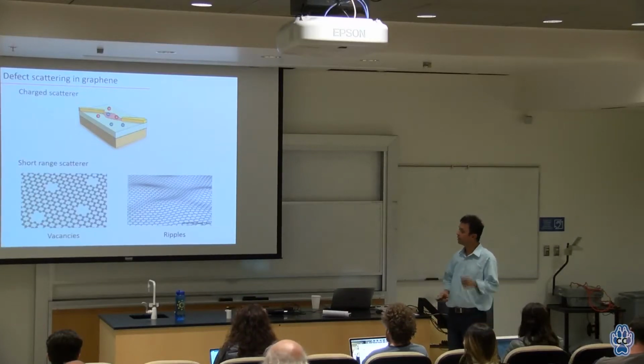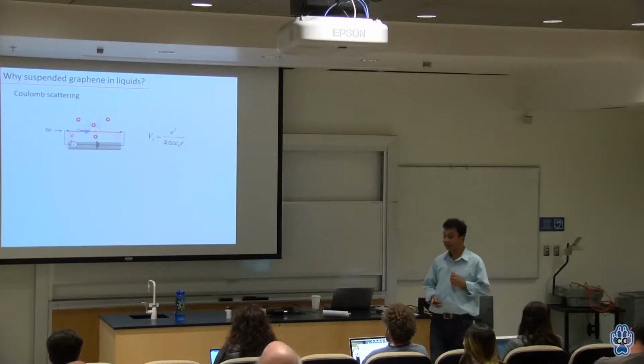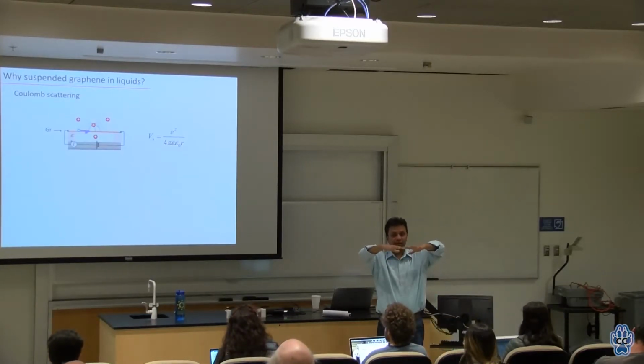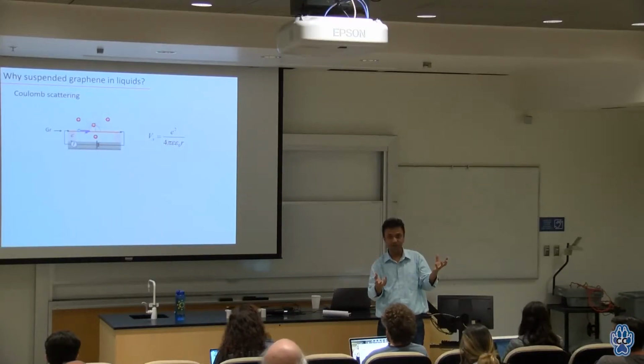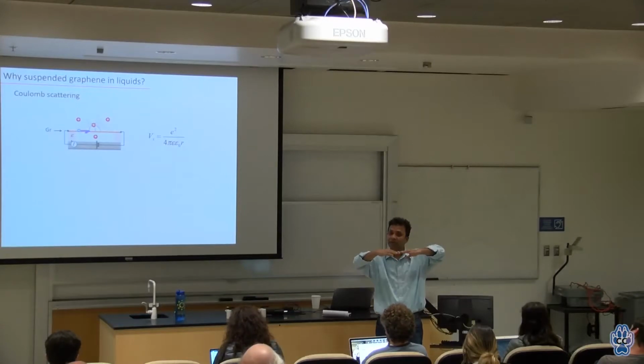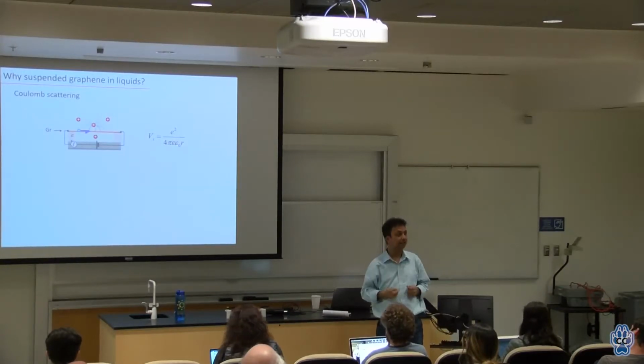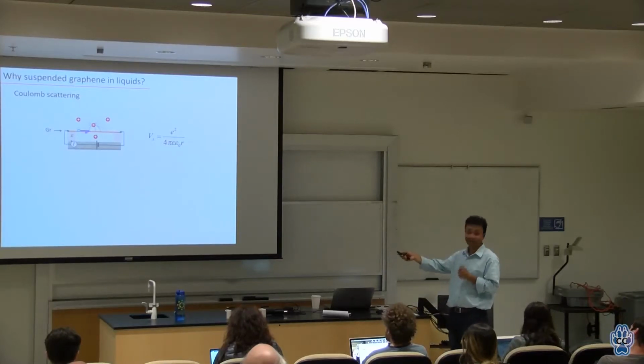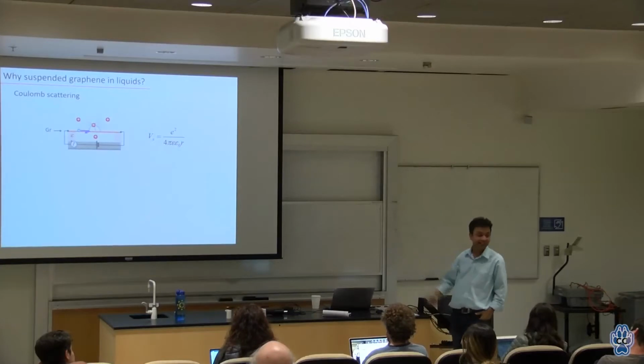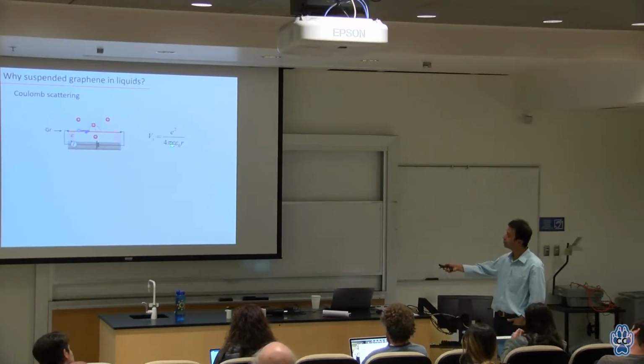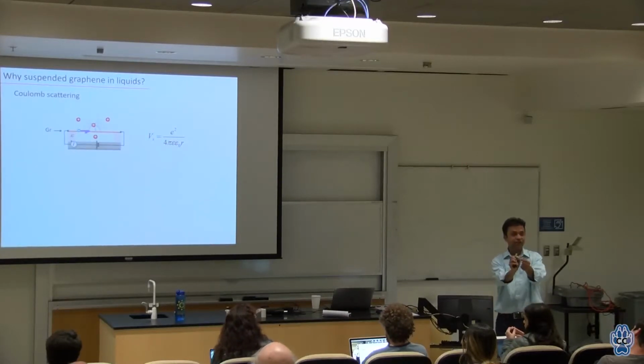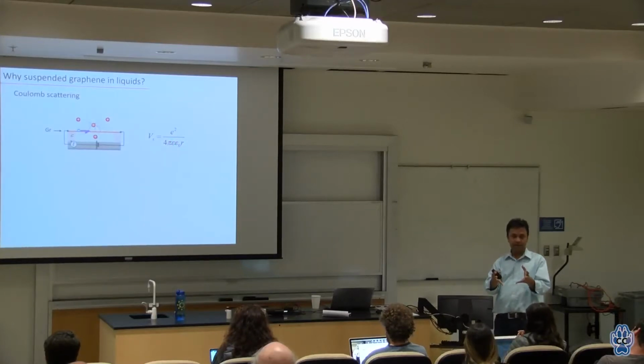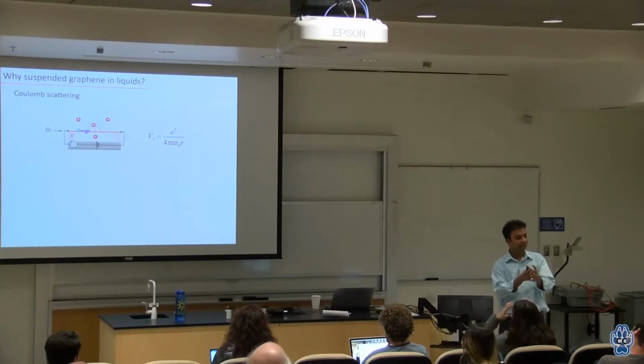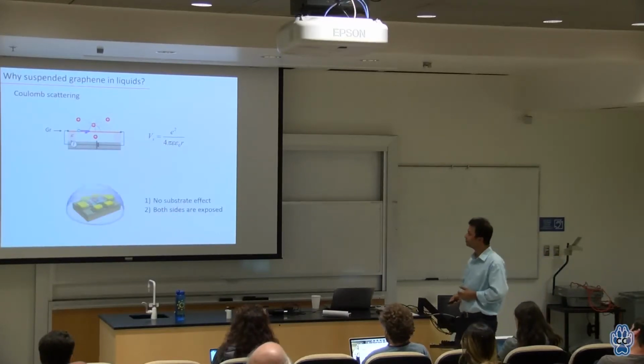So what we did is some control experiments. We created suspended graphene monolayer samples in dielectric liquid, because every liquid has a dielectric property. So you can have a sample in a dielectric environment, flush the liquid, and put in a new dielectric material. That means you can tune the dielectric constant. As you all remember, this is Coulomb's law, and Coulomb's law has this dielectric constant. So our goal was to vary this dielectric constant and see, this is your scattering strength. If I increase it very, very large, what would happen? This scattering potential will go down, and then my electron should see smaller scattering. So that is what we did.